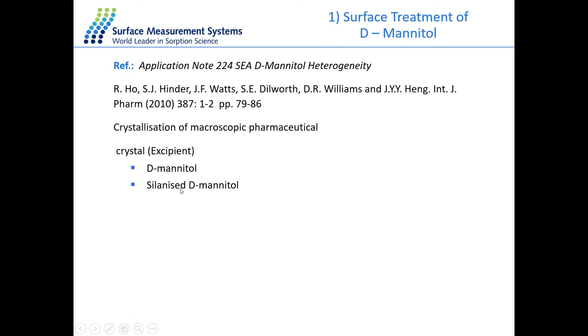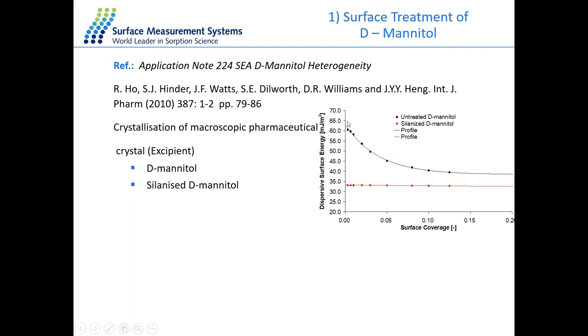We measured the surface energy of both mannitol samples. Here the blue line shows the surface energy of the untreated D-mannitol. As you can see, the surface energy on the y-axis is changing as a function of the surface coverage. That means on the untreated D-mannitol, there are different levels of energy sites on the surface. It has both high energy sites as well as low energy sites. The sample is very heterogeneous on the surface.